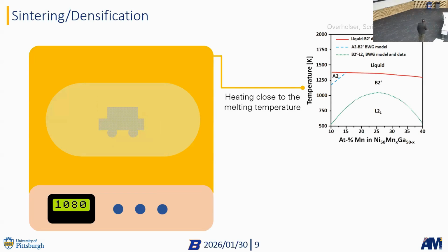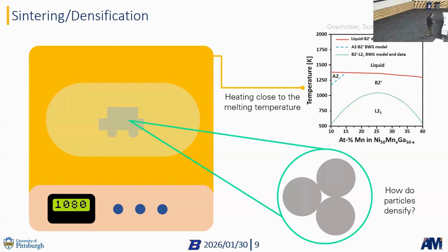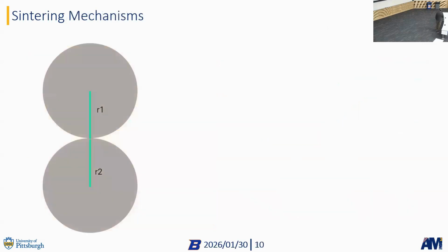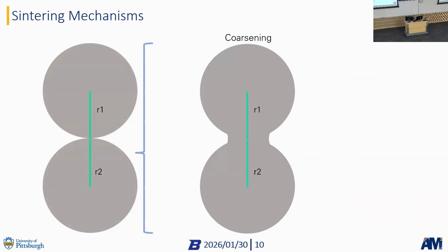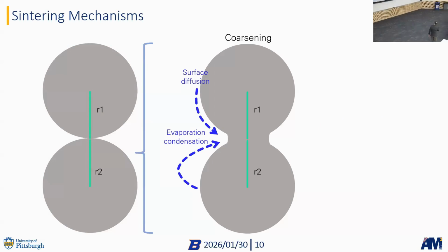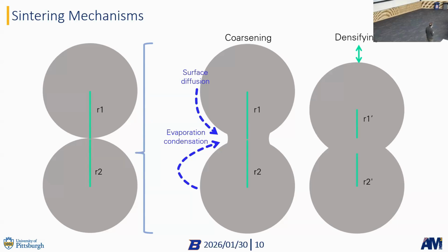And as I already mentioned, we need to be very close to the liquidus line here, right, to densify quite a bit. But how does this densification actually work? So if we're looking at our sintering process, initially we have just powder particles that are next to each other. They are touching a little bit, right? During the sintering process, we have first a coarsening step where we have necking starting between those powder particles. And then we have, through surface diffusion and evaporation condensation. And then we have the densification step as well, where we have volume diffusion and grain boundary diffusion as the mechanisms of densification.